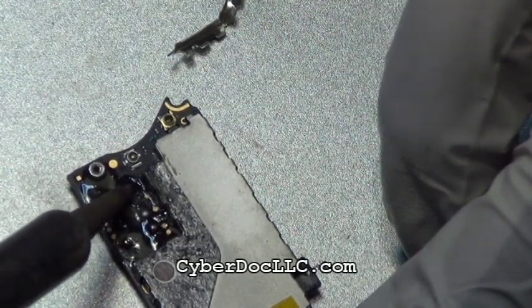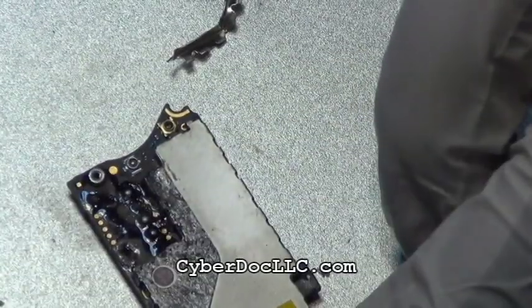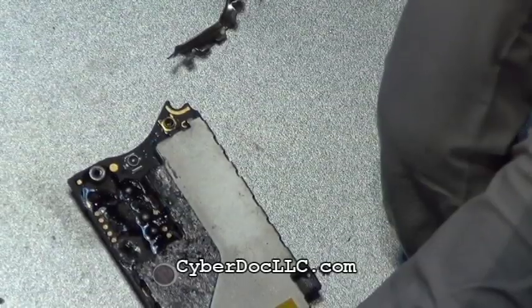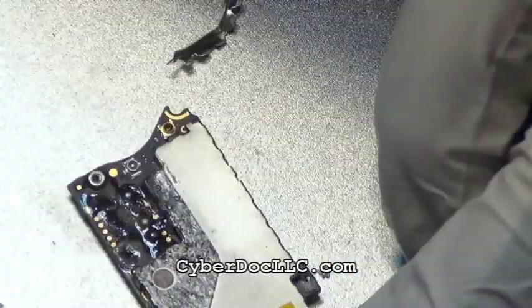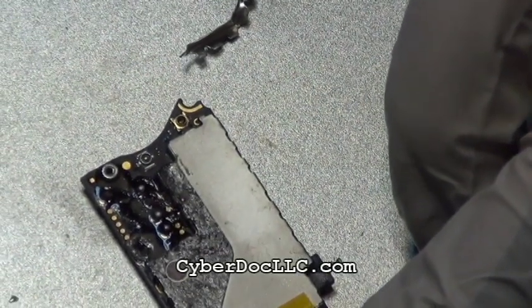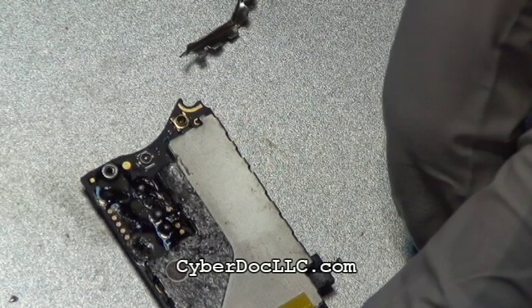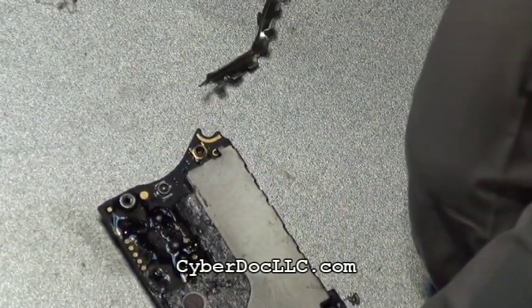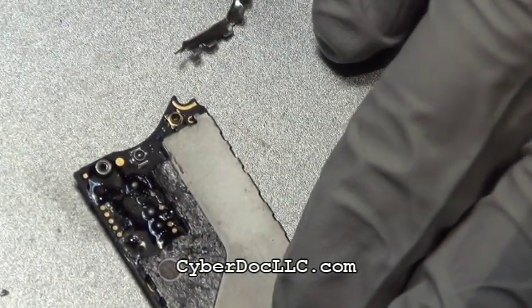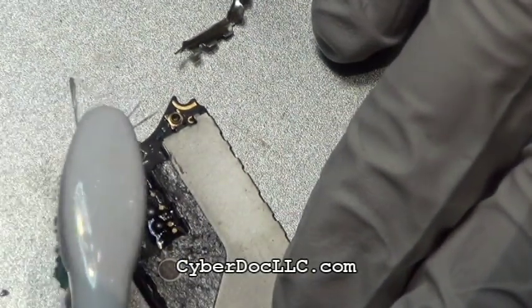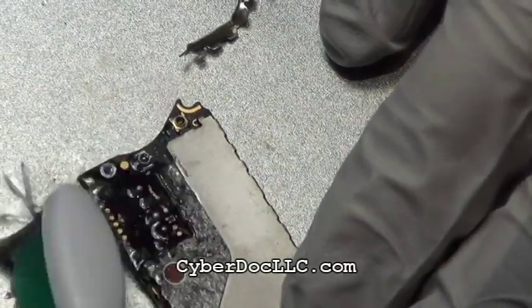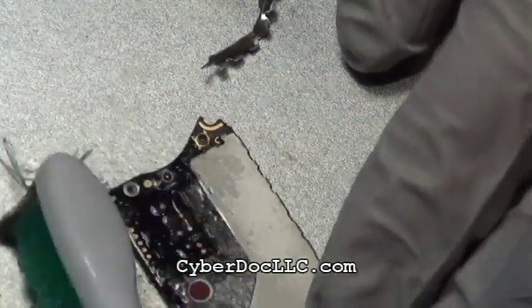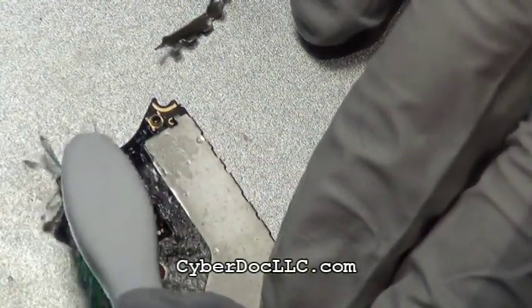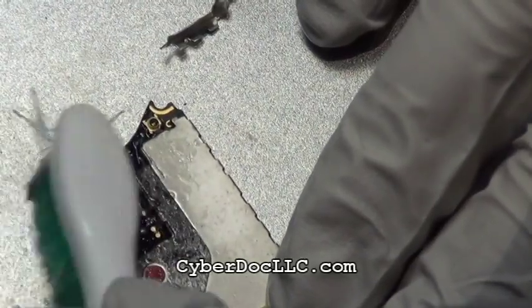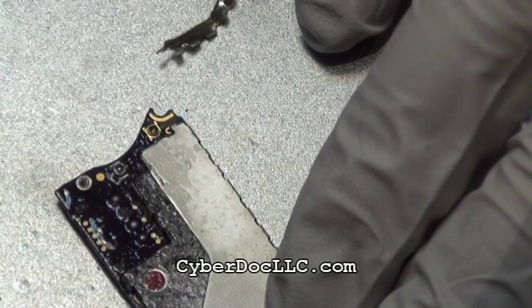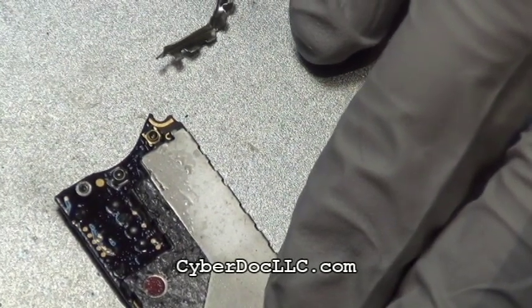Now you see this solder paste is really small. If you watch it under the microscope, it's really, really teeny, 20 to 30, 40 microns I believe, little solder balls. When you heat it up, it will melt, then it becomes solder. So that's what the gray stuff is, the solder paste. Once you tin the pads with the new paste I put on, which melts at 137 degrees Celsius, you want to clean the rest of the residues and little solder balls that are on the logic board right now. You don't want those to stay on the logic board.